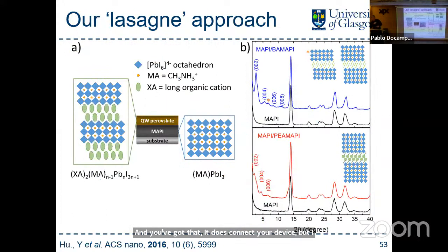But if you use the lasagna approach, so you put a layered perovskite on top of your film by converting the top surface, you kind of get a bit of both. You get the good charge transfer of the archetypal, classic 3D perovskite, and now my top layer has these really nice big bulky cations, hydrophobic, more stable. We're on the money. Things are looking good.